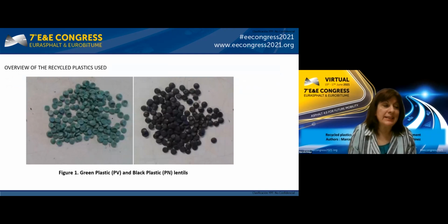Two homogeneous recycled plastic types in granulate form were first analyzed and then used. One of these recycled plastics was composed of opaque green plastic lentils coded PV in this study, and the other was made of black plastic lentils coded PN. Each lentil had a mean diameter of 5 millimeters with a mean weight of 30 milligrams, with an important hardness. The PB material was obtained from recycled used drums that had contained agrochemicals. This drum had been triple washed and punctured for their conditioning, as stated by the Argentine standard for the safe, responsible handling of such waste materials.